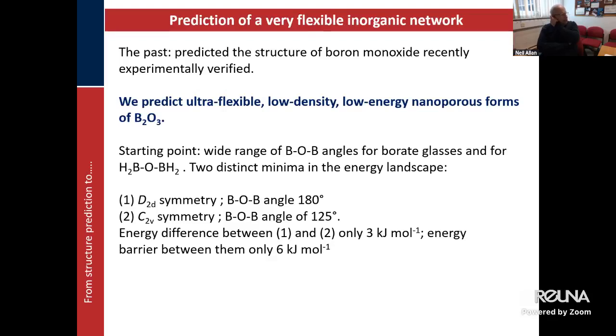And what we first did of that, so we moved away from the rather esoteric boron monoxide simply to boron oxide, B2O3, the well-known one. And first of all, we predicted very flexible, low density, porous forms of B2O3. And actually, there's loads of these.